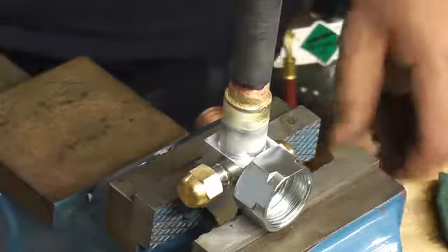Okay, so let's take a look at our joints here. And we'll start off with just the last one that we did. This is our copper to steel joint. And you can see we cleaned up to about here. You can see the scratches from the sandcloth. Even though we cleaned it with the sandcloth, we didn't put flux up here. So you can see it's nice and shiny and clean here, but then you have a demarcation line of the oxidization, and that's where the flux wasn't. So all this shiny spot here is where the flux was. You can see we're nice and sealed all the way around. That is just a flux mark, that's not a hole. You can see it comes right off.